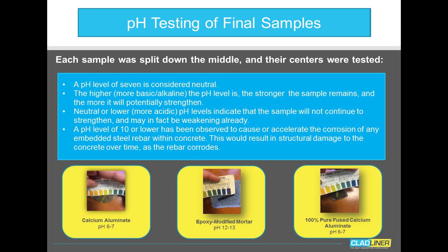The epoxy-modified mortar, however, kept its pH up very high, and in fact, you can tell if you look very carefully here in the central picture, if you look at the epoxy-modified mortar that has a high pH, the corrosion was actually nullified on the outside and almost created a barrier or a layer beyond which the acidity did not carry or transfer.